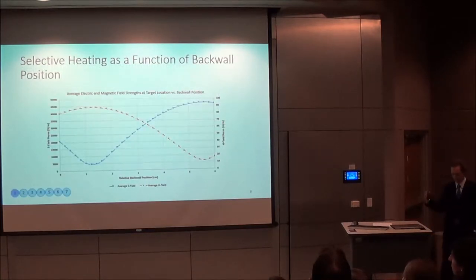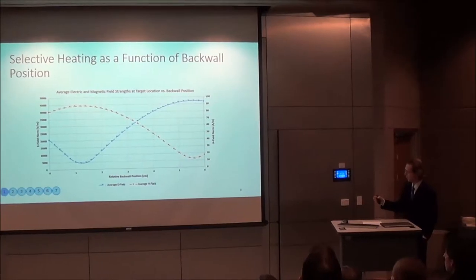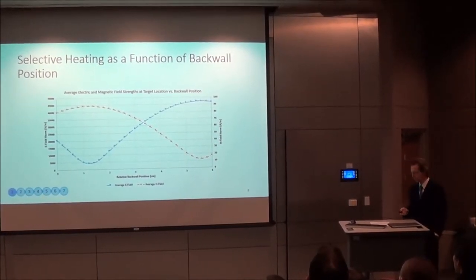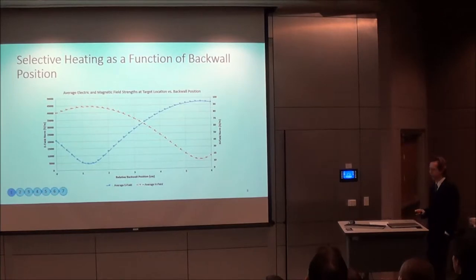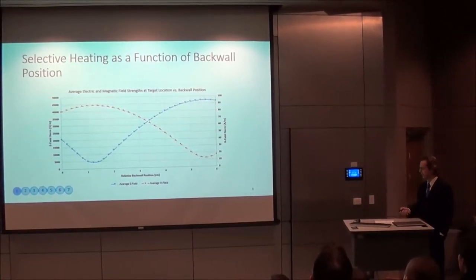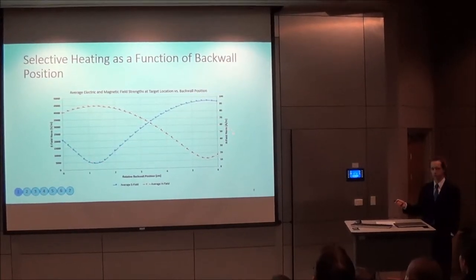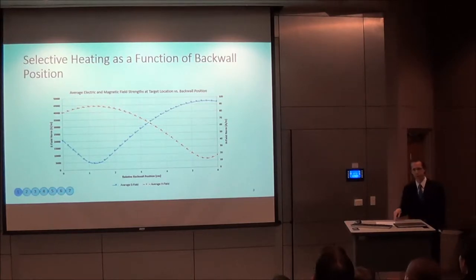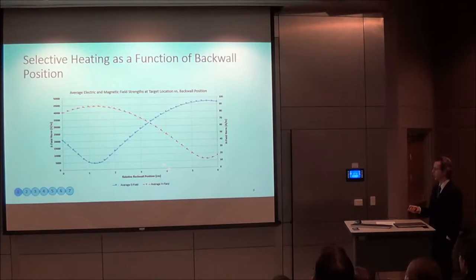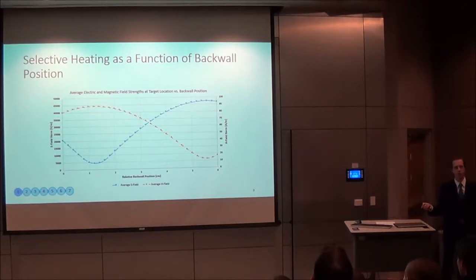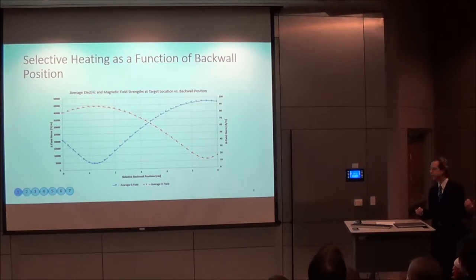And so using the standing wave pattern I showed you in the electric and magnetic field, if you place a target in a particular position in the waveguide and move the back wall of the waveguide, then the electric field intensity, represented by the blue line, and the magnetic field intensity, represented by the orange line, at the target location can be varied. And this intensity for an empty waveguide with no distortion caused by anything present in it basically follows a sinusoidal pattern, where the two field components are exactly out of phase with each other. This gives us the potential application to be able to selectively heat only in the magnetic field or only in the electric field.